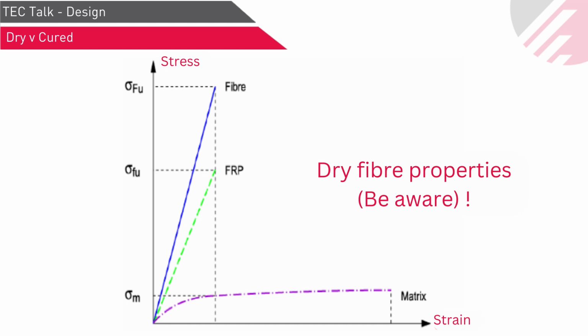So we could see on this stress strain behavior, the blue line shows the behavior of just the fiber only, which shows very high strength and low strain values and everything. And then we have the epoxy matrix property as well in purple. And then when they are mixed together, then the behavior of carbon fiber or FRP will come. That is called the composite laminate property. So FRP should always be designed based on this final cured laminate property, and not just the dry fiber, which is a common mistake made in the past by the designers.